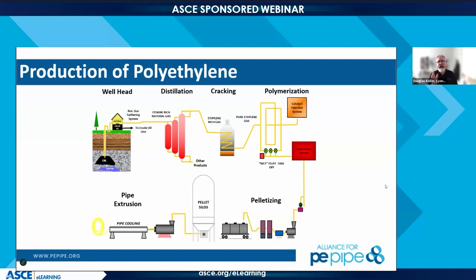Out of the gas portion, which is methane, propane, ethane, butane, the methane is what goes to your house for heating and cooking. We take off the ethane. So we take that ethane to a step called distillation, where we purify it and make sure that what we have is pure ethane. We then go to a step called cracking. Cracking is where we take the ethane, we open it up and create a double bond between the two carbons that are present in ethane, turning it into ethylene.